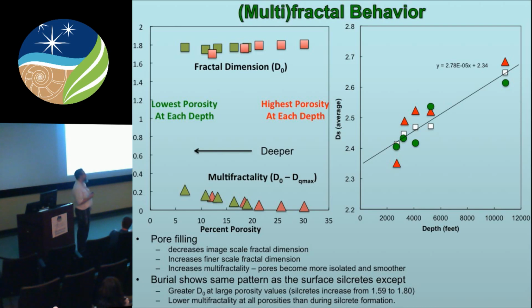At the image scales, this is percent porosity. So as the sample is compacting, you're moving to the left. That's deeper, to your left on this one. And you can see that the overall or average fractal dimension, that's D0 in the multifractal analysis, an average non-scale dependent fractal dimension, tends to get smaller. That means things are getting smoother as we go deeper at the image scales. However, they're also becoming more multifractal. That is, the dependence on scale of the fractal dimension is increasing.